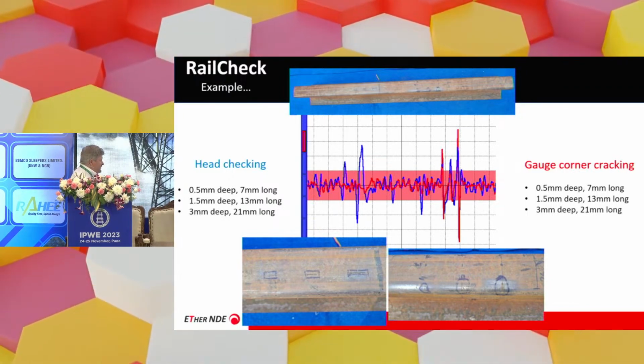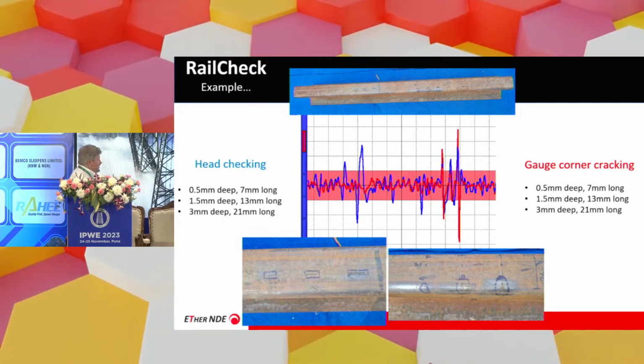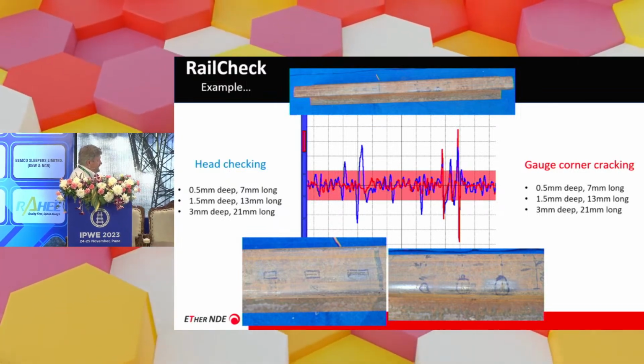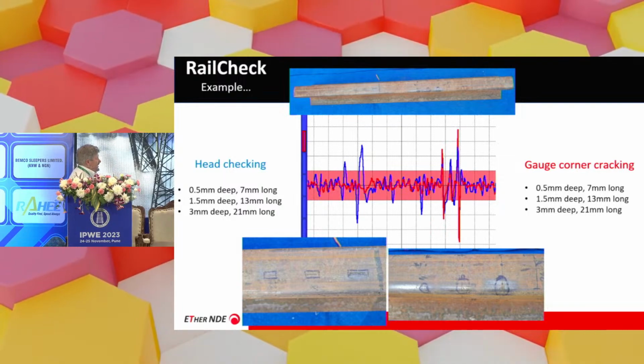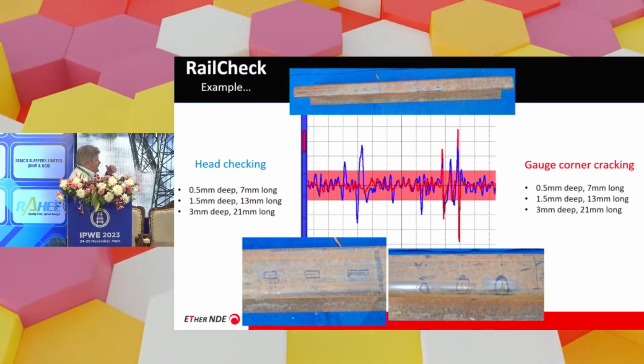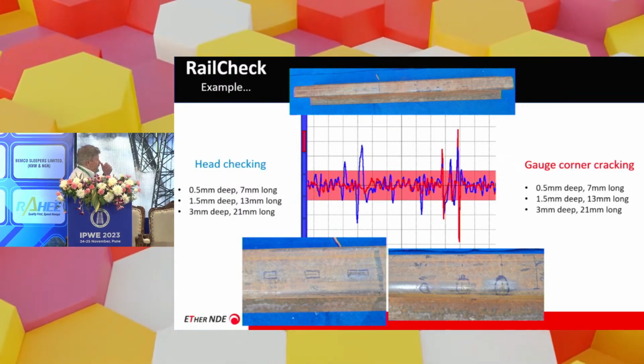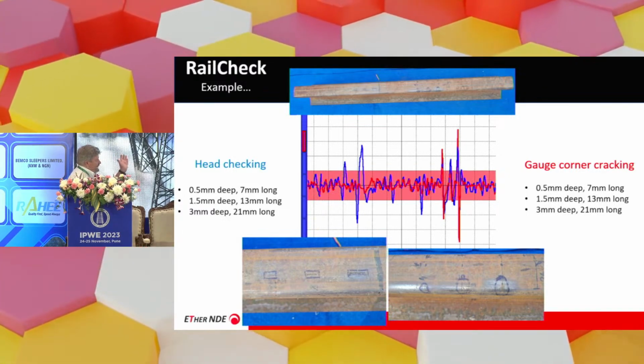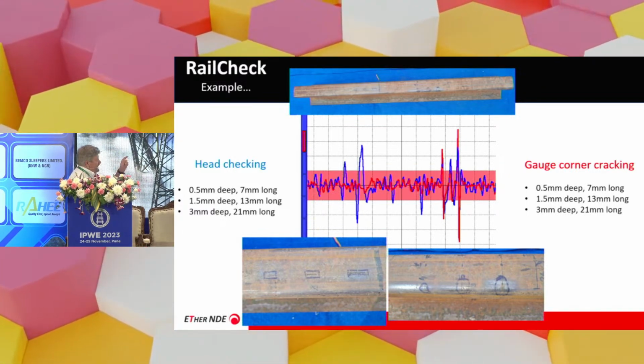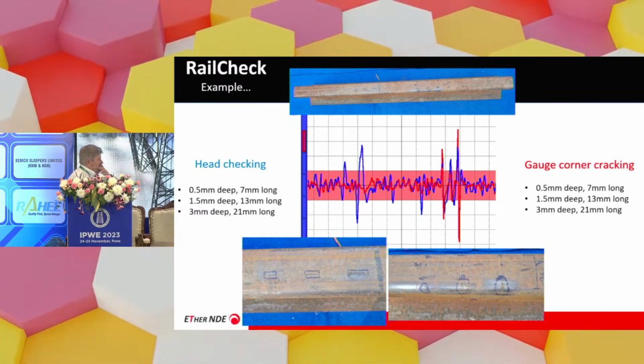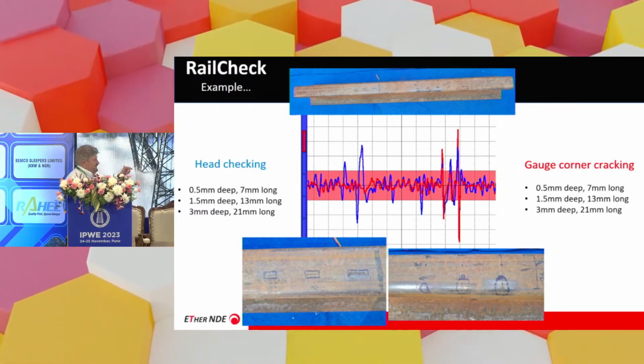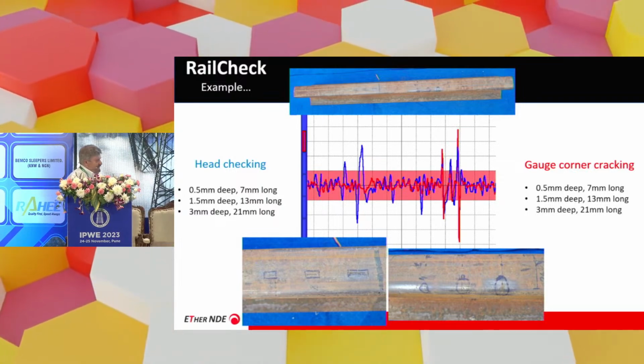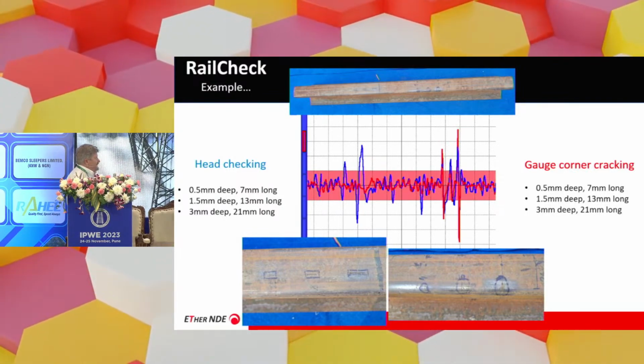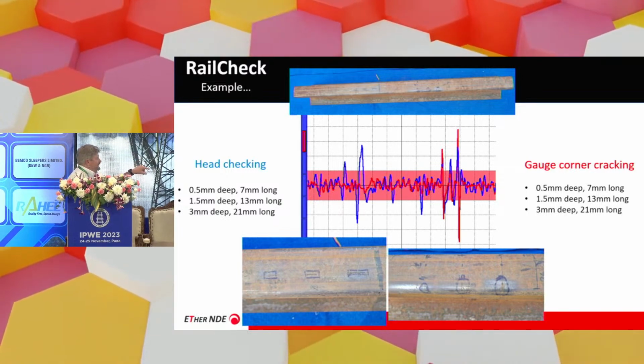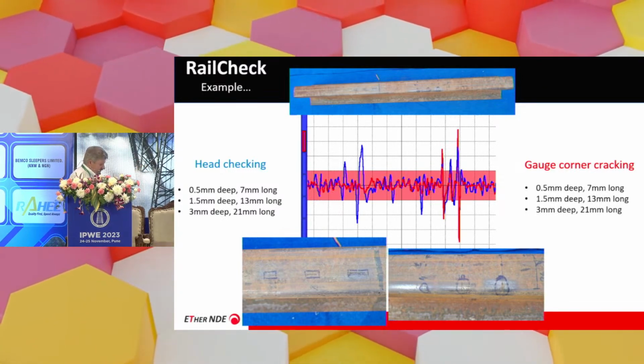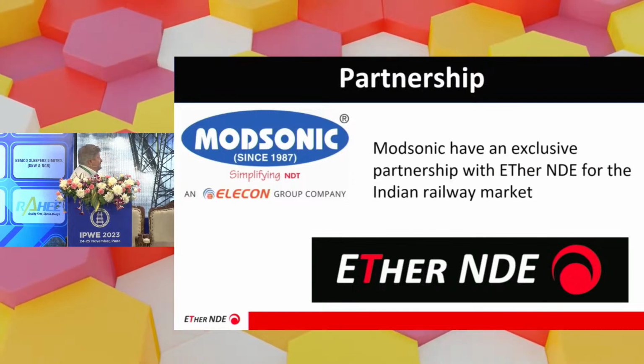If we now go onto the gauge corner, you can see these 1, 2 and 3 responses on the right-hand side. On the left, the longitudinal defects are in blue, and on the right-hand side we're now getting red and blue spikes in the same place. That confirms these defects are in fact gauge corner cracks, and the severity changes in line with the relative size of the defects.